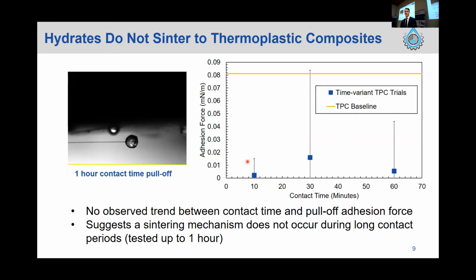And basically what you can see here is that there is no general trend to this data. And what to take out of that is basically that a sintering mechanism doesn't begin to dominate over these longer contact times, where that was seen with carbon steel, that there was a chemical interaction that would begin to dominate that adhesion and really increase that adhesion force between the particle and the substrate. And that was observed up to 1 hour. So again, both of these, the baseline and the time-dependent pull-offs, were shown to have a relatively low adhesion force.